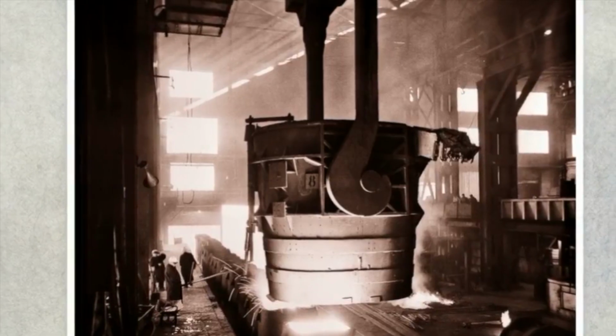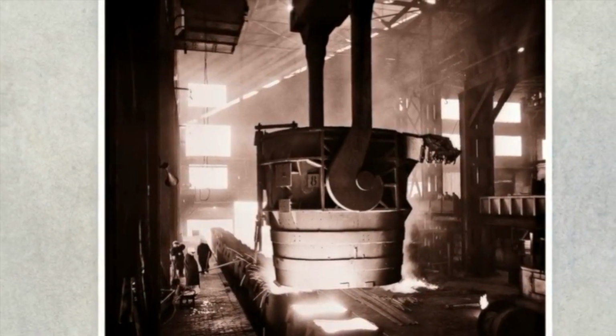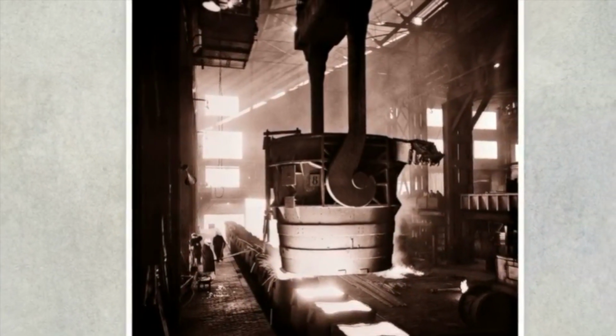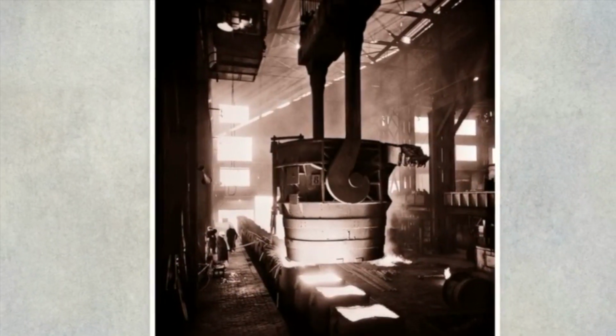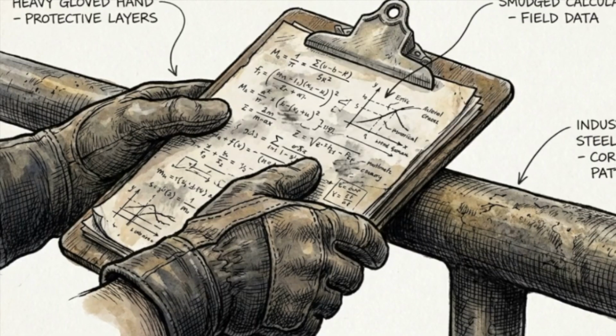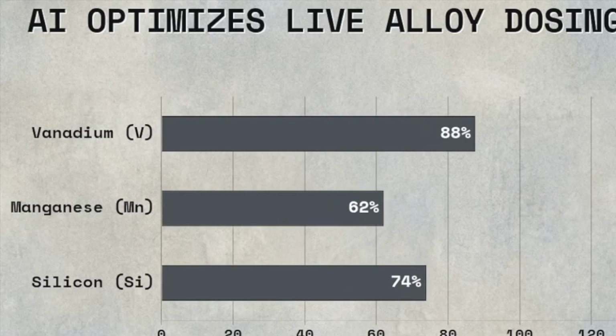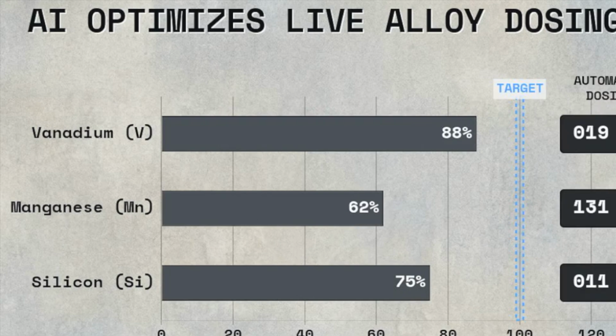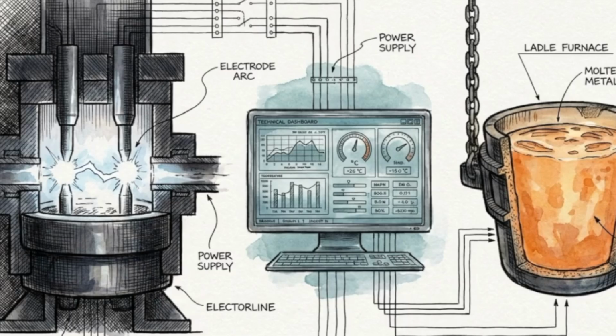Optimizing the arc furnace alone is a mistake. Efficiency depends on the chemistry requirements downstream at the ladle furnace. In the ladle furnace, operators have historically relied on manual calculations. Miscalculations lead to expensive overalloying or off-spec heats. AI models now calculate automated alloy dosing. They combine live spectrometer data with recovery models to remove the guesswork. True optimization requires a connected intelligence that manages data from the arc furnace mast to the final ladle chemistry targets.